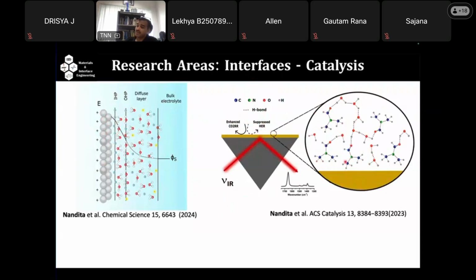This is one of the questions we asked, and we found that by adding some small amount of molecules, in this particular work, we have shown that adding some dimethyl formamide, you can actually bring a hydrogen bonding at the interface, very selectively at the interface, and the strong hydrogen bond will form a semi-solid-like water. This actually suppresses the hydrogen evolution reaction, hydrogen generation from water, but it enhances other proton-coupled reactions like the carbon dioxide reduction reaction. So this is a very interesting thing.